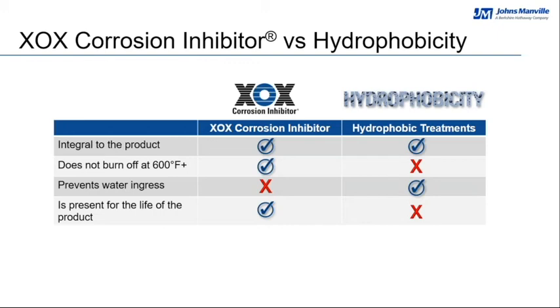Whereas the materials that are treated with an active corrosion inhibitor, like the XOX product offered by Johns Manville, this is, again, integral to the insulation material. It is not a topical treatment of any kind. It does not oxidize or burn off at elevated temperatures, up to and including the maximum operating temperature of 1200 degrees Fahrenheit for these materials. It is not designed to prevent water ingress. It's actually designed to be a safety net in the event that water ingress does occur, and it is something that is present for the life of the product.